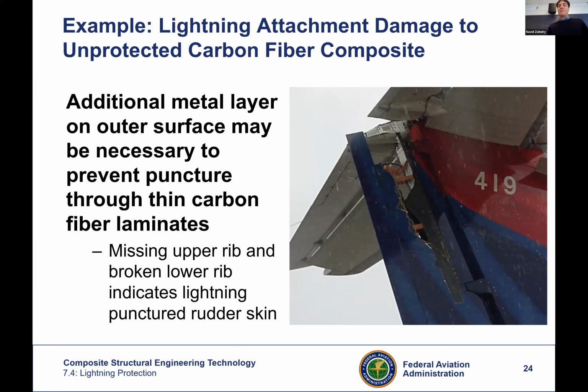Here's another example, a puncture through the composite. And this happens if the design is a bit thin. If you have a thin design that cannot handle that amount of energy, then it's going to puncture through the thin design. So at very critical locations, you have to either increase the thickness of the design, or the better thing is to add a metal layer on the outer surface. And that metal layer's job is only to dissipate the energy from critical locations. So we'll come up with different strategies to do this.